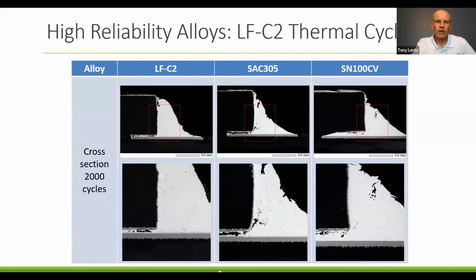Here's cross sections after 2000 cycles of the solder joints on those components. You can see LFC2 on the left has very little cracking. It looks very clean. It looks like the solder joint's pretty well intact. In the center is SAC305. SAC305 has pretty good cracking going on there, and potentially those cracks would meet in the center somewhere and probably lift that component right off the circuit board. And then SN100CV on the right shows kind of cracking behavior in between those two, just like the performance metric showed on the last slide. And that's what the cross section is showing us.